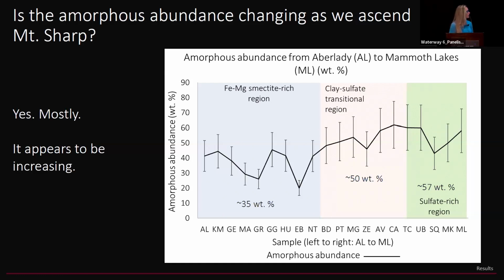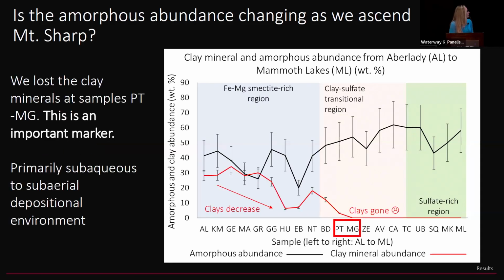So this is what the amorphous abundance looks like, and this is what the errors look like as well. You can see in Glentoran, we have around 35 weight%, and as we move into the sulfate transitional region, it's around 50, and then it looks like it's starting to increase maybe less dramatically than from the smectite to the sulfate transitional region, and it's about 57 weight%.